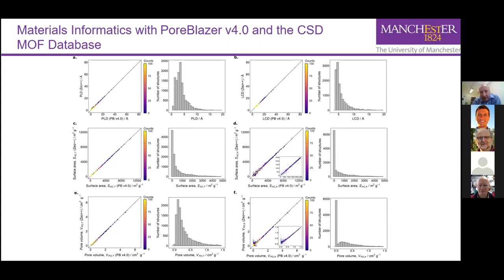Another interesting property of this database of porous materials is that, from the point of view of the distribution of properties, these materials are all very, very microporous. They feature very, very tiny pores. And so the vast majority of these metal-organic frameworks simply are not porous enough to be, let's say, practically interesting for chemical engineering applications. And they are themselves already a subset of around 100,000 metal-organic frameworks, with the remaining 90% of them being even non-porous. So we need to be mindful of a much smaller group of porous materials that actually have some practical interest, practical applications.